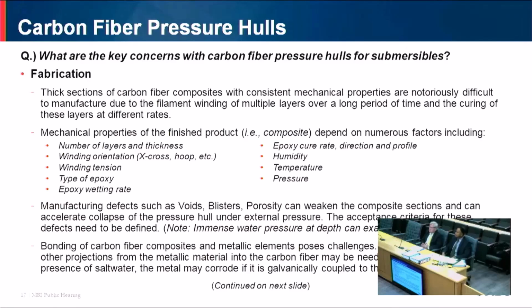So the next thing that's challenging is bonding of carbon fiber composites with metallic elements. Typically, if you bond a carbon fiber composite with a metal, you'll have projections coming out of the metal. Typically, you will have fins, and these projections go into the carbon fiber composite, and they help in getting better adhesion. So in addition to applying an adhesive, you have to have co-lamination. That ensures you have better adhesion between the carbon fiber composite and the metallic element. Now, galvanic corrosion is an important consideration here because if the metal comes in contact with the carbon fiber strands in the presence of seawater, you can have galvanic corrosion. This typically occurs in steels and aluminum, and that can cause corrosion of the metallic members.